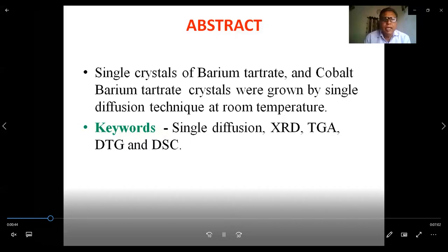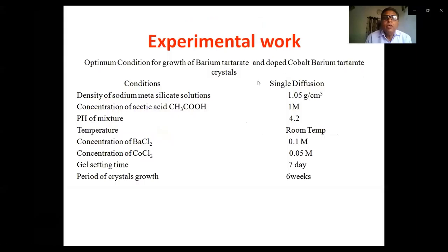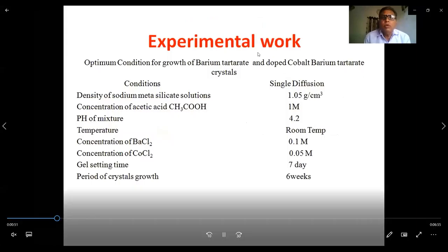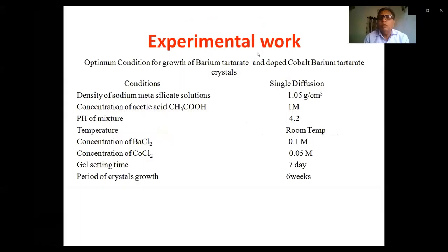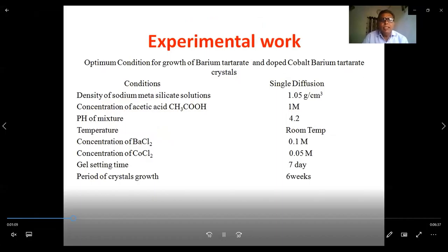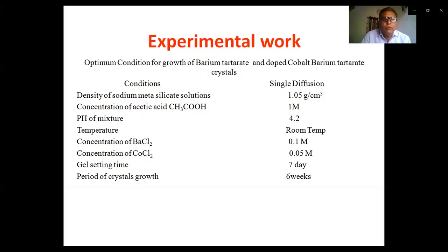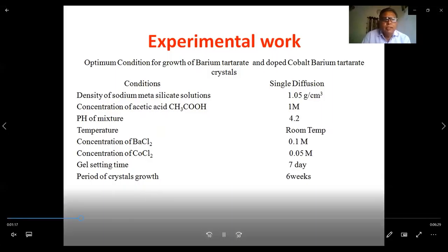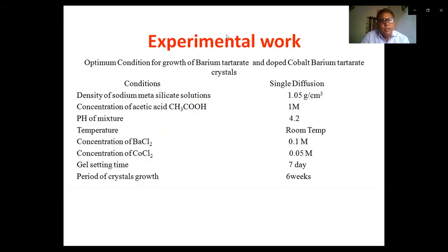My experimental work shows the optimum conditions for both barium tartarate and cobalt barium tartarate. Single diffusion conditions: density of sodium metasilicate solution is 1.05 gram per cubic centimeter. Concentration of acetic acid is 1 molar. pH of the mixture is 4.2. Temperature is room temperature. Concentration of barium chloride is 0.1 molar and concentration of cobalt chloride is 0.05. Gel setting time is 7 days, and period of crystal growth is 6 weeks.